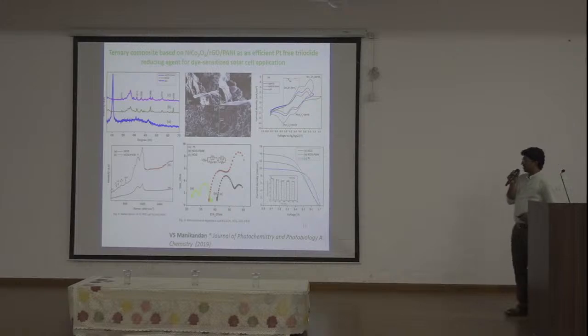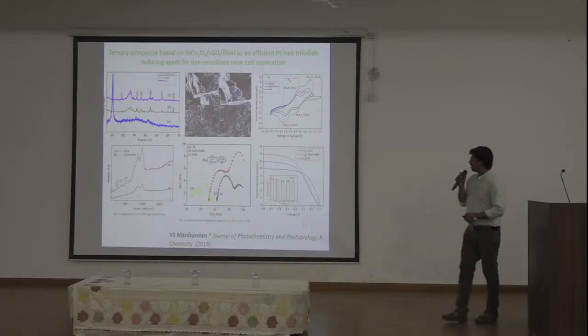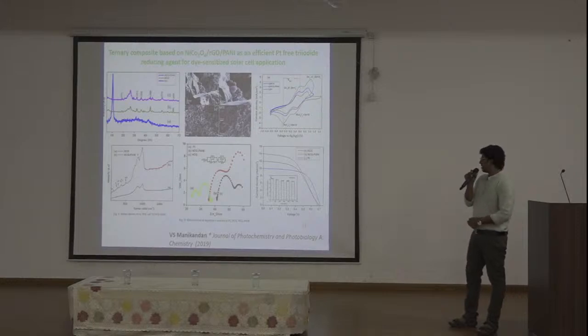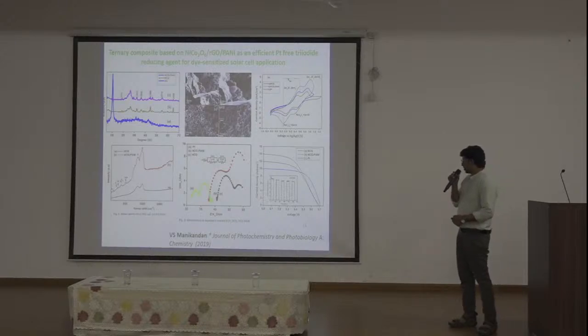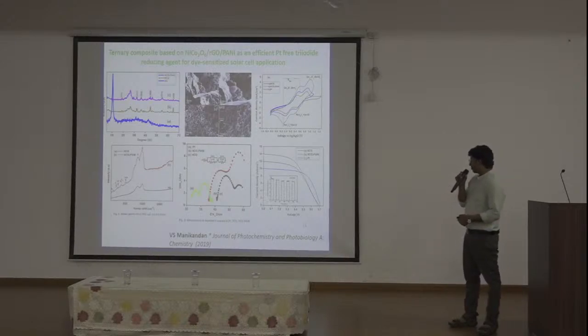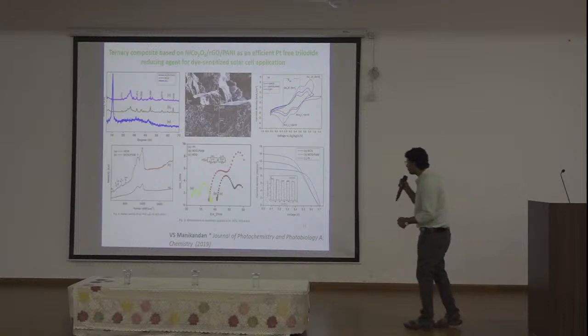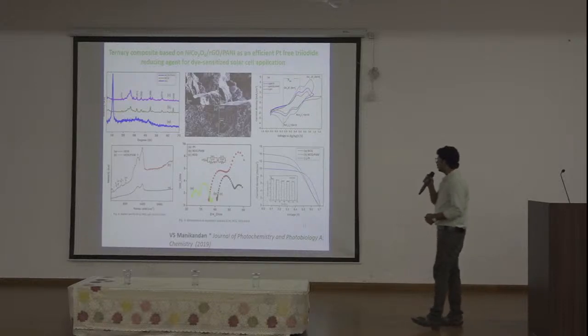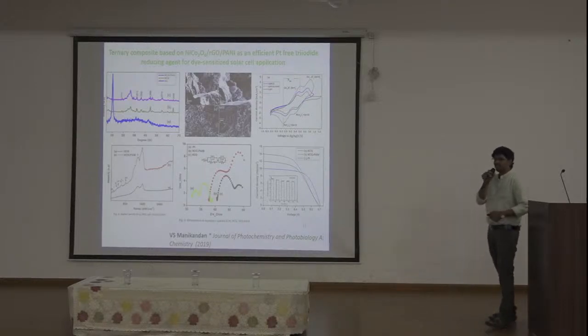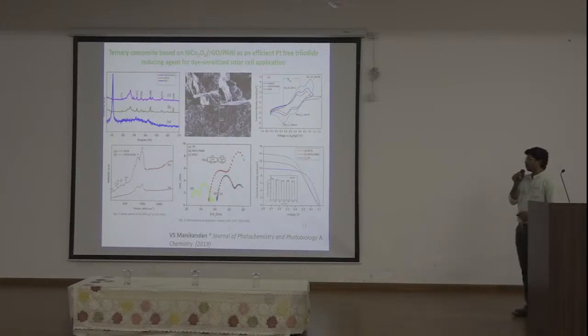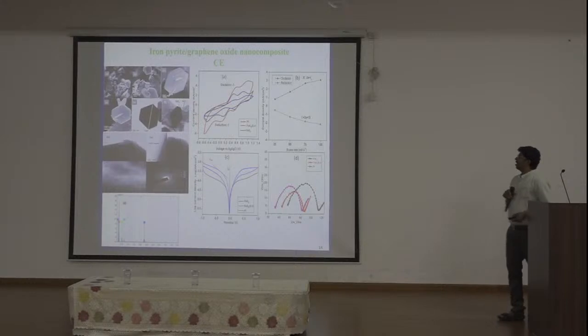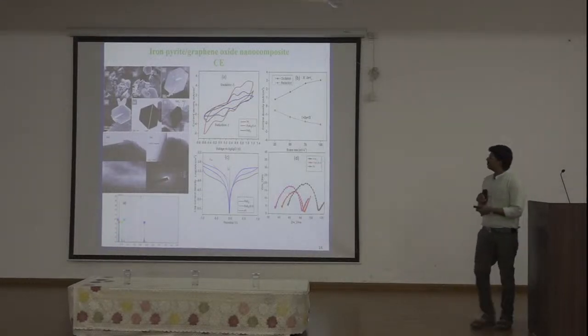Also, we have tried to check how the device works over several cycles, like 600 minutes of on and off conditions. There is no change in the current density value. We can see the same current density value, which directly implies the stability of the devices.